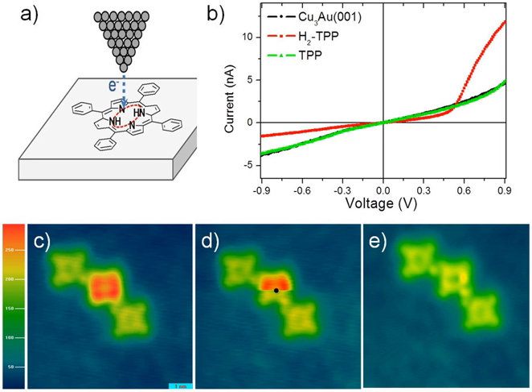Another encountered artifact is when the electrodes undergo chemical reactions due to the high field strength in the gap. When the voltage bias is reversed, the reaction will cause hysteresis in the measurements that can be interpreted as being of molecular origin. A metallic grain between the electrodes can act as a single electron transistor by the mechanism described above, thus resembling the traits of a molecular transistor. This artifact is especially common with nanogaps produced by the electromigration method.